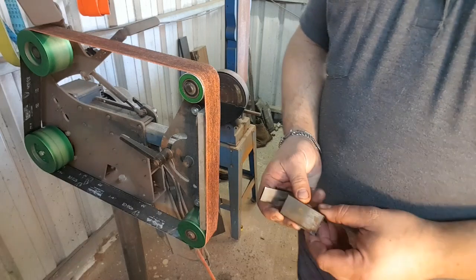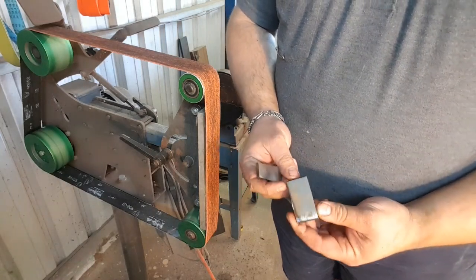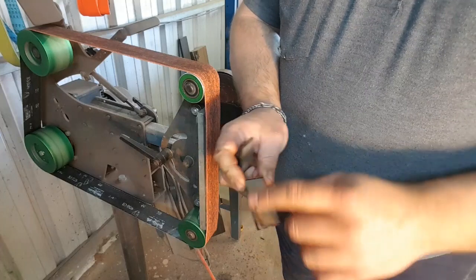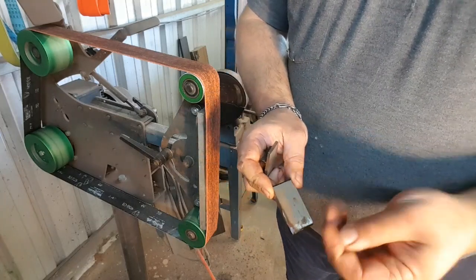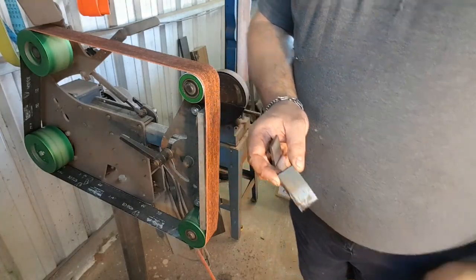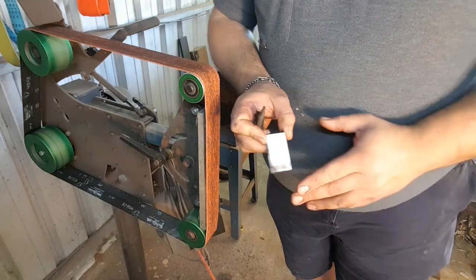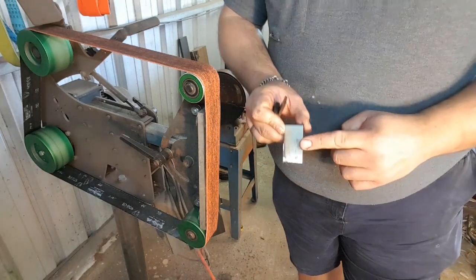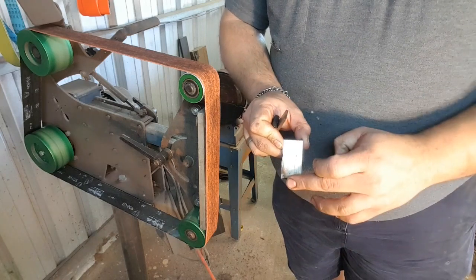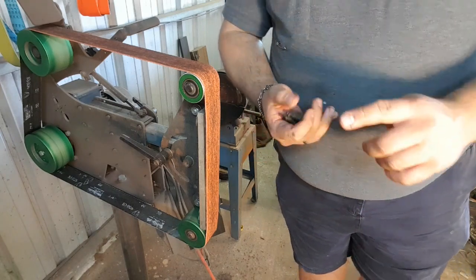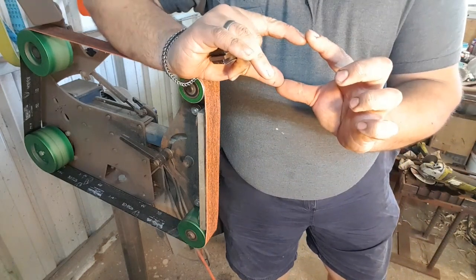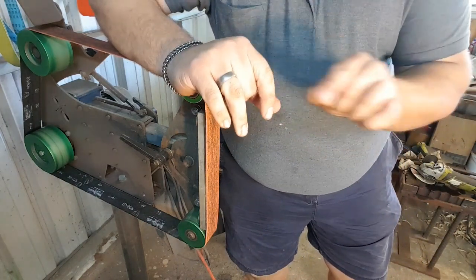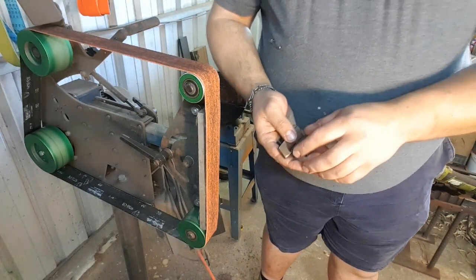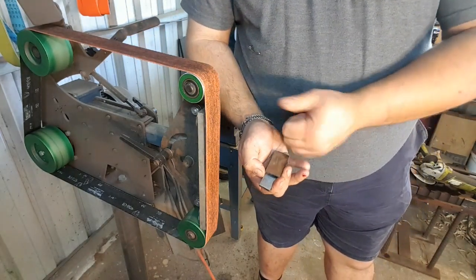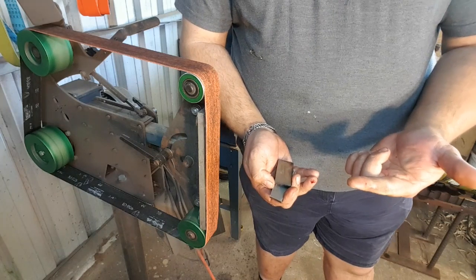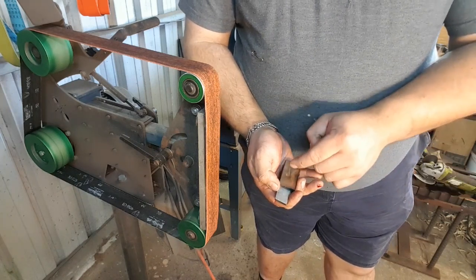So when preparing a Damascus billet, the first thing we need to do is clean these surfaces. I'm also going to chamfer each edge just to give myself a little bit more leeway for the borax to squirt out. In the event that you're doing this with an angle grinder, try and grind more from the edges than from the center. In the end, having something that looks ovular in shape is much better than having something that's got a dish in the middle. Because remember, at the end of the day, what we're trying to do is have the borax squirt out of the join before it gets trapped inside the steel.